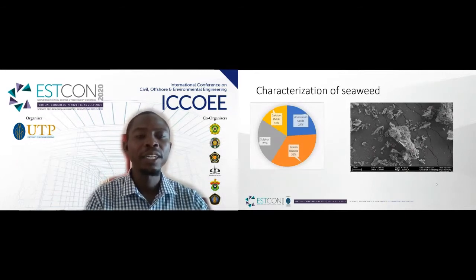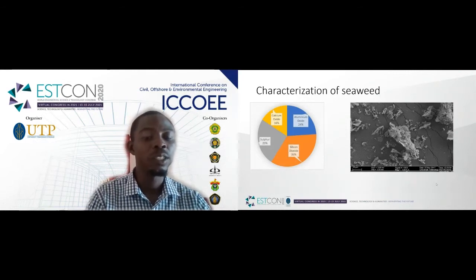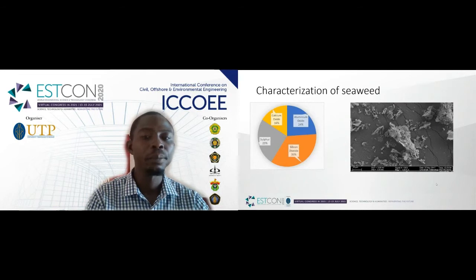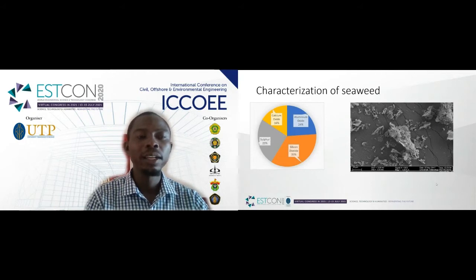Seaweed ash characterization. The XRD result revealed calcium oxide is 16%, aluminum oxide is 24%, silicon dioxide is 35%, and sulfur content is 25%. The FESEM image showed clear cellulosic fiber shape with fibril.